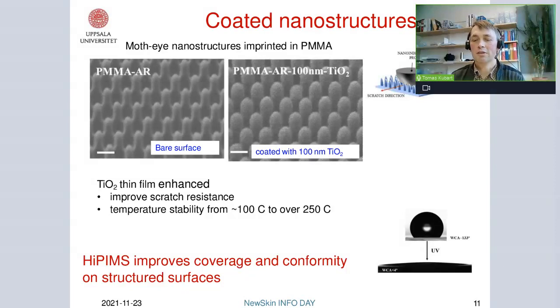And I'm slowly running out of time, so I will conclude with my last example, again a different topic. At some point, it's interesting to combine surface structuring and surface coatings. This is an example of a nanostructured surface, a moth-eye nanostructure that's imprinted in a polymer material. Of course, such nanostructures are wonderful. They have really great properties, but they are mechanically not very strong. So here we've shown that if we coat such a surface with a thin layer of titanium oxide, we can improve both the thermal stability and the mechanical properties of the surface. And because titanium oxide is also photocatalytic, we could even make the surface super hydrophilic after UV illumination.